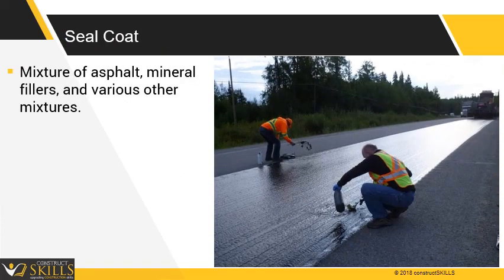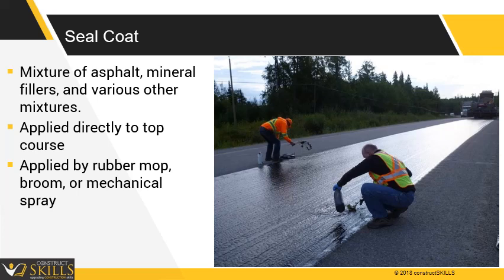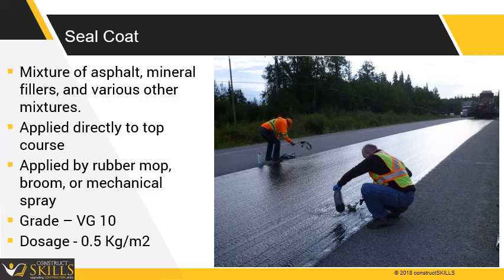Seal coat is a mixture of asphalt, mineral fillers, and various other materials, which can be applied directly to the top surface of an asphalt pavement. It can be applied by rubber mop, broom, or mechanical spray. Bitumen of grade VG10 should be used and dosage should be 0.5 kg per square meter. The function of seal coat is primarily to waterproof the pavement.